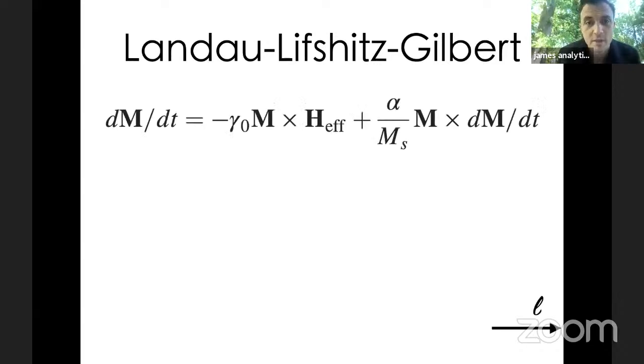Okay, so again, I won't dwell on this too much because there's quite a bit to get through, and I'm sure a lot of this is familiar to many of you. But the way the dynamics of this is understood is through what's known as the Landau-Lifshitz-Gilbert equation, where you have two components with which we understand the rotation of the spins of the antiferromagnet, and that's what's known as a field-like term and an anti-damping term. Here you've got the magnetization, which is the local magnetization of the spin in the system.